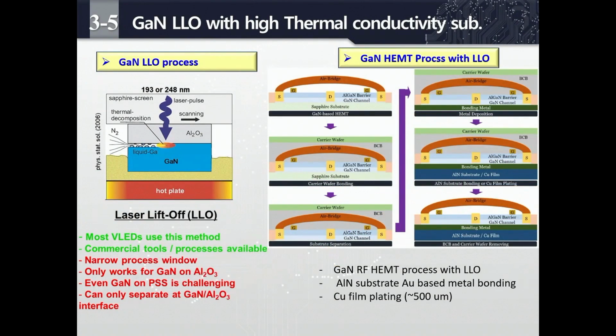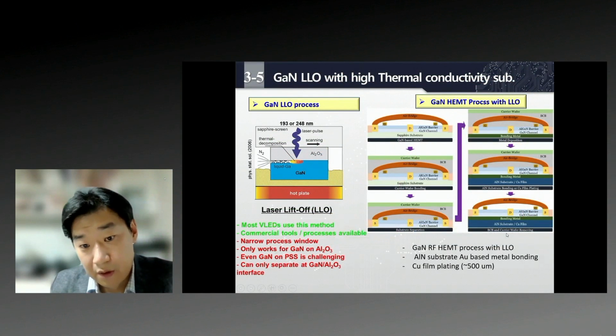The final approach is using gallium nitride laser lift-off techniques. Laser lift-off is quite a typical method in the LED area. So we used a 193 or 248 nanometer laser pulse. We melt the gallium nitride, and after that we can get thin gallium nitride epi layers. With this idea, we tried processing the GaN HEMT with the LLO. First, we make an RF GaN HEMT device here. And then we do BCB wafer bonding. And then we remove the sapphire substrate. And then we add an aluminum nitride substrate with the bonding metal, or copper film plating. After that, we remove the carrier wafer and the BCB. The copper film and the aluminum nitride thickness are quite similar, at around 500 micrometers.